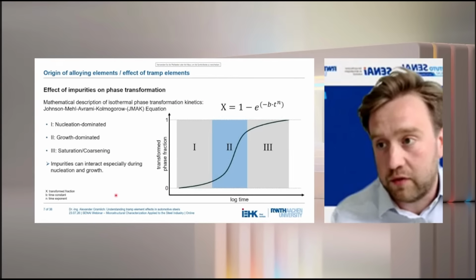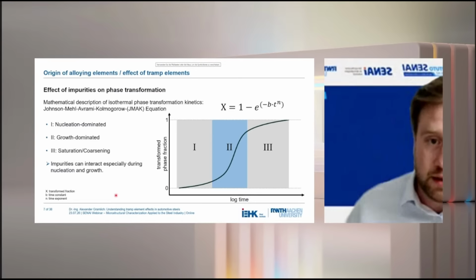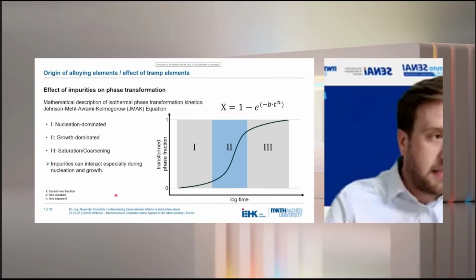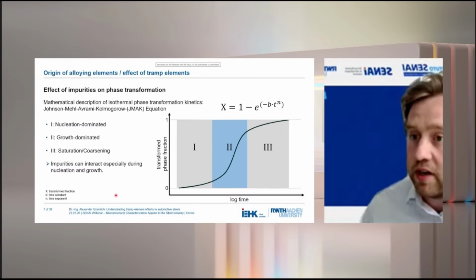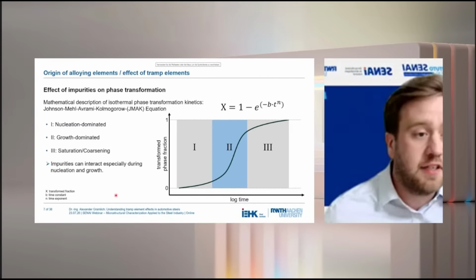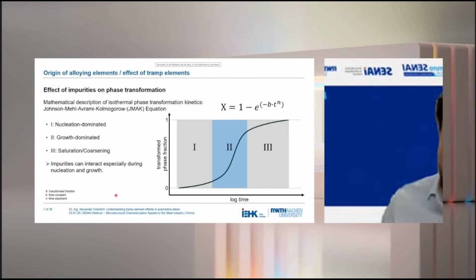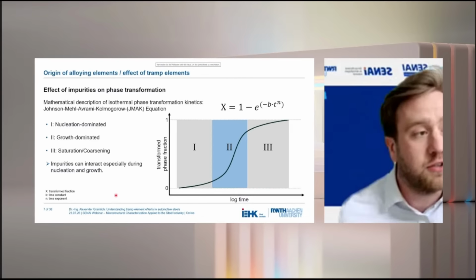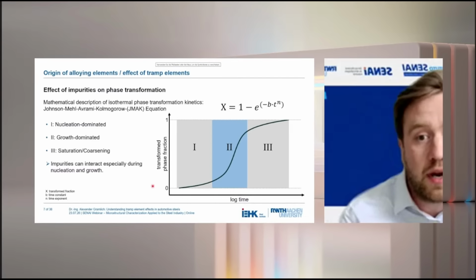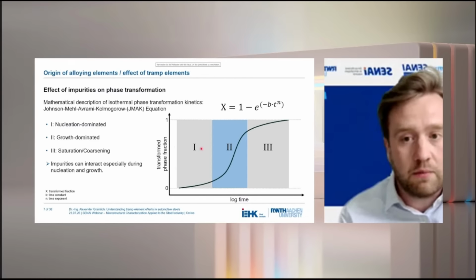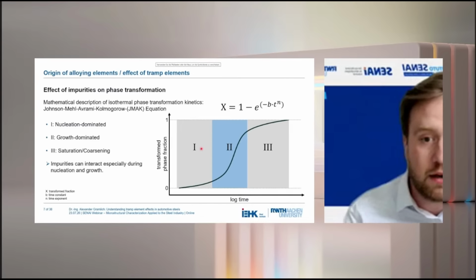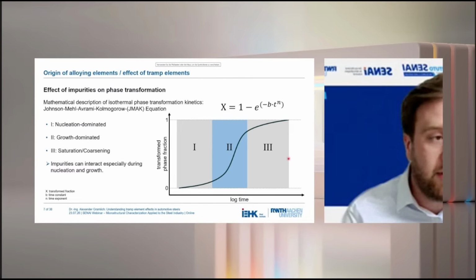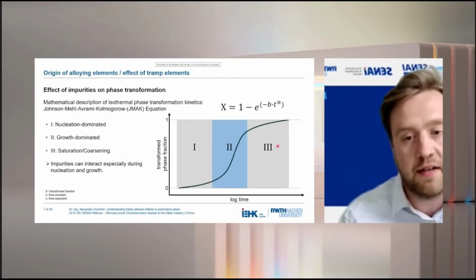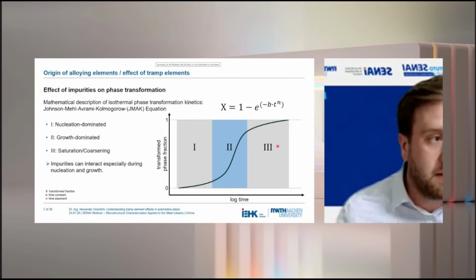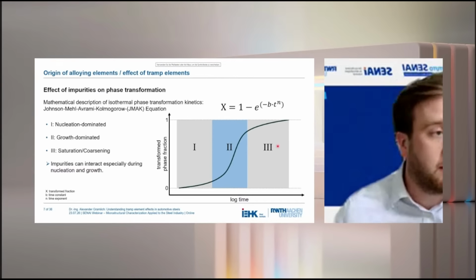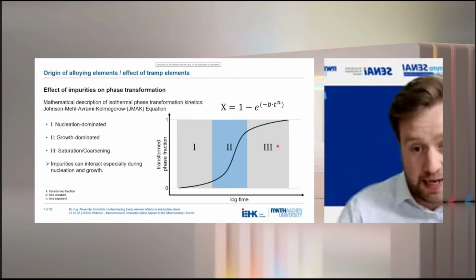And I will start with this equation here, the JMAK equation, basically a standard equation for material engineers. And this gives you an idea about the phase transformation kinetics. So usually when we are talking about phase transformations, we have a nucleation dominated area, a growth dominated area, and a saturation, so coarsening dominated area. And this is independent of whether it's a phase which is forming like austenite or ferrite or a precipitate.